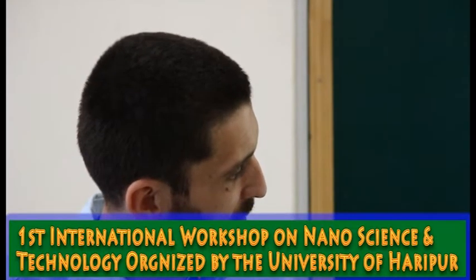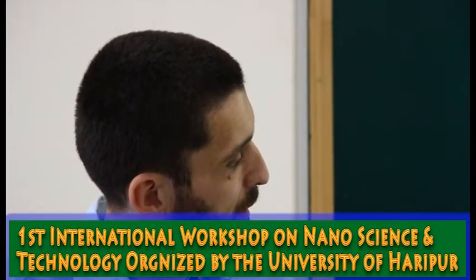This is an example of dry etching. This is the deep reactive ion etching. The system is pretty simple. You have the substrate, generally silicon, derived from the industry, and you have the suitable mask, generally a metallic mask. By using a suitable gas for the substrate that you are using, you can selectively remove the silicon on the exposed area. Then you passivate the structure that you need. Then you etch again, and you replicate this cycle many times, obtaining these deep structures here. These are some examples of structures that we produced with this technology of deep reactive ion etching.